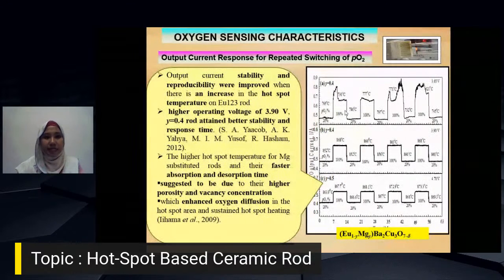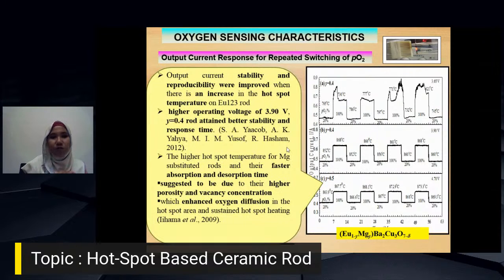You can see that increasing the substitution of magnesium to 0.4 attains better stability and response time. The higher hotspot temperature for the magnesium-substituted rod, and their faster absorption and desorption time. So it shows that when you substitute magnesium, the higher hotspot temperature means the response time can improve, meaning faster absorption and desorption time at the hotspot.